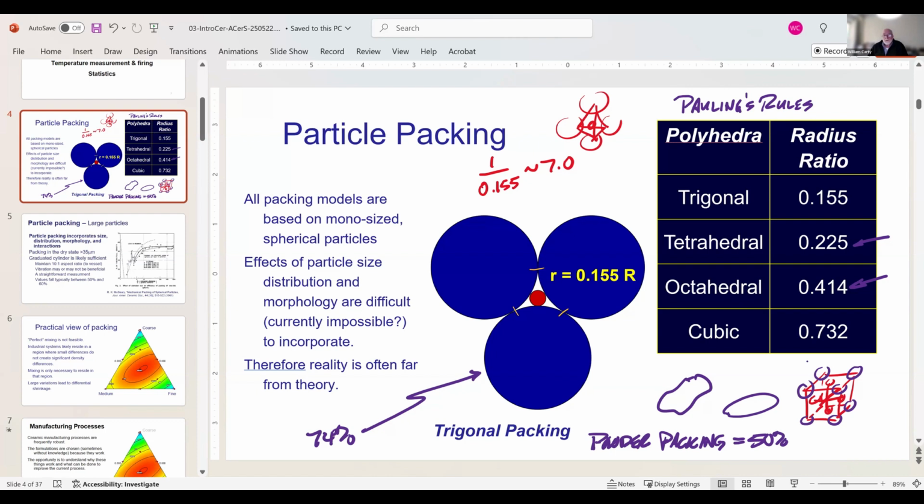Turns out it packs to 50%. You can get that value for sand with a graduated cylinder. Okay, so it's not complicated. So I got 50% calculated. They had something like 53,000 tons of sand, and they had estimated 51 and a half. So we were pretty close. But anyway, packing behavior, 50%.